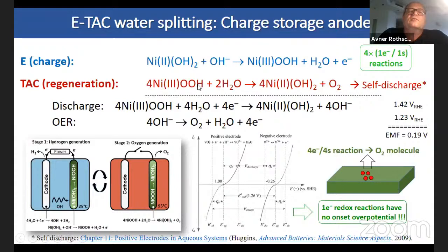Here you can see that, if you look at the regeneration reaction that occurs spontaneously, conceptually, you can split it into an anodic and cathodic reaction that occur spontaneously at the same electrode in different regions. And then you see that these two reactions are simply the discharge reaction and the oxygen evolution reaction. And the electromotive force, or the potential difference between the two of them, gives you an electromotive force of nearly 200 millivolts, which is the reason why this reaction is spontaneous.